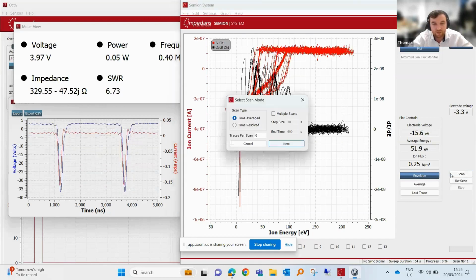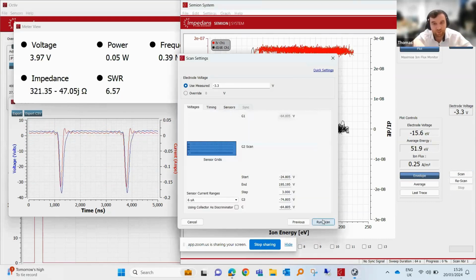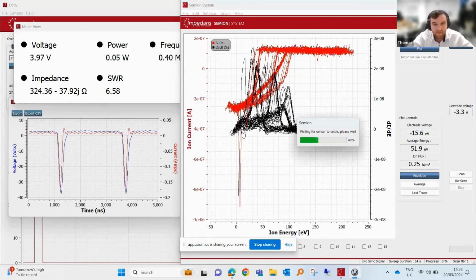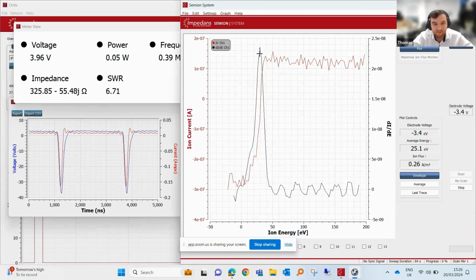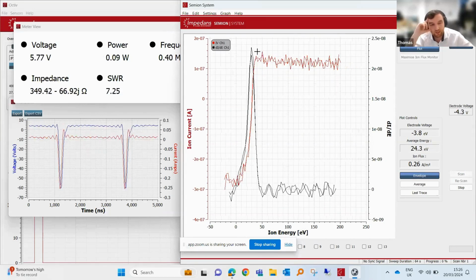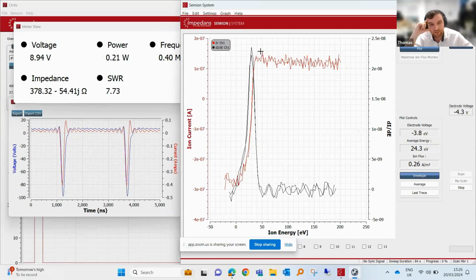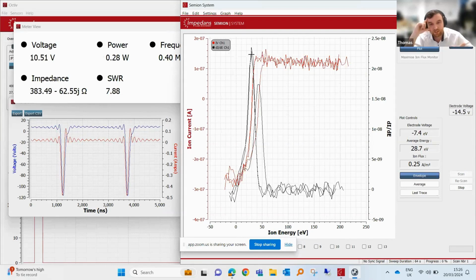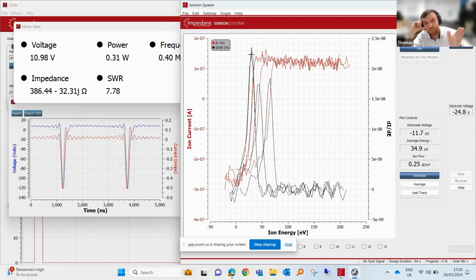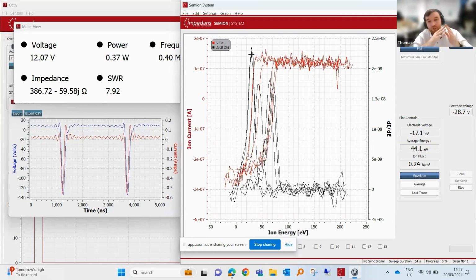Okay, we're just going to restart the scan so we clear the screen. Perfect. At the moment we're at about minus 40, and we're going to minus 50, 60, 70. Now you can see that the energy peak is increasing, but we're still keeping the narrow band, unlike with a sinusoidal, where you get broader and broader distributions as you increase the energy.